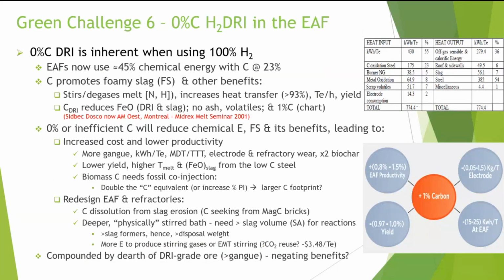The sixth challenge is the zero carbon hydrogen DRI in the EAF. You can see from the top chart that only 55% in this particular case has come from electricity. In terms of energy, 23% is coming from carbon oxidation. Carbon, as I said earlier, promotes the foamy slag. And with that comes stirring of the melt, increased heat transfer. And the carbon in the DRI currently reduces the FeO, both in the DRI and in the slag. And it also has the benefit of no ash, no volatiles.